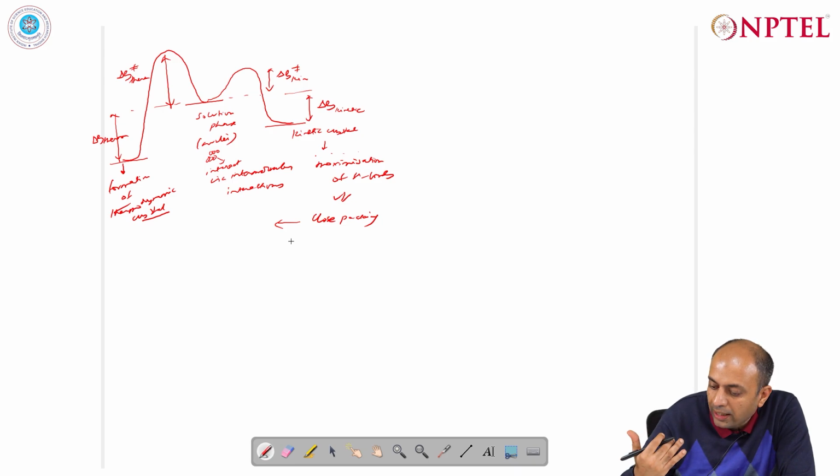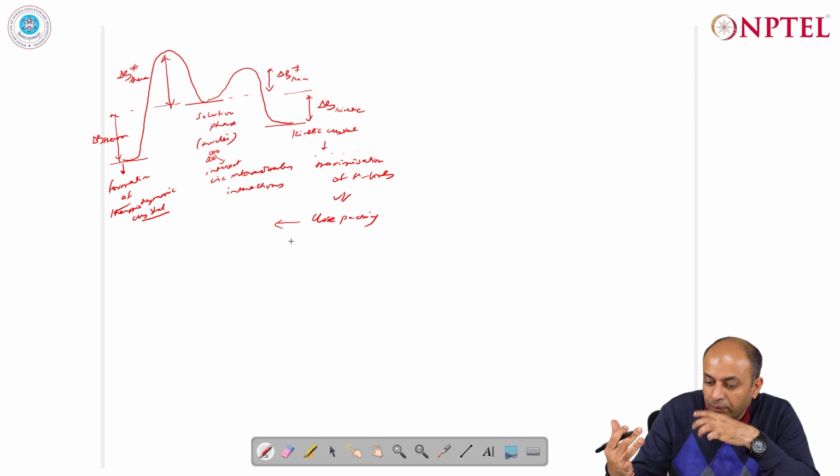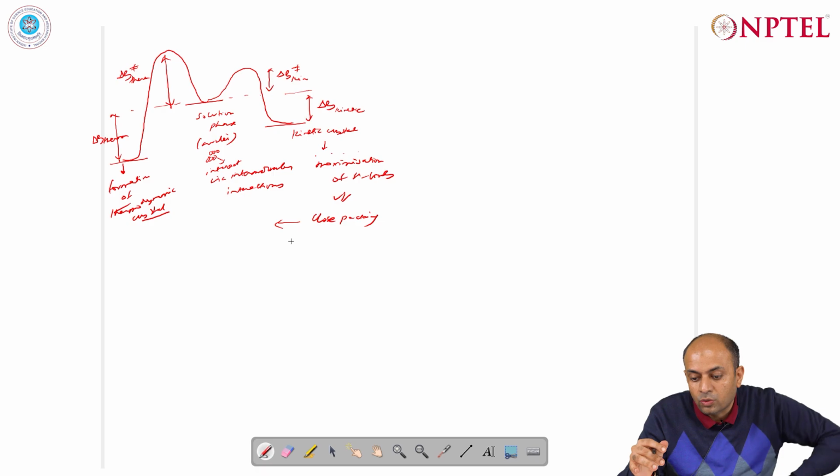Whereas if you want the formation of supramolecular synthons which maximize highly directional and short hydrogen bonds, then the tendency to form a kinetic crystal is greater. And once this hydrogen bond array is formed in solution, again these are quite stable, and it is very difficult to disrupt this hydrogen bonding structure and convert it back into the monomers, from where it can possibly go into the thermodynamic form where the close packing principles operate. So it is the competition between this maximization of hydrogen bonds and close packing which actually leads to kinetic and thermodynamic polymorphs.